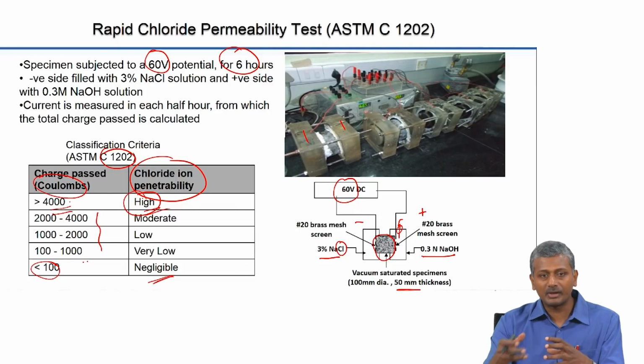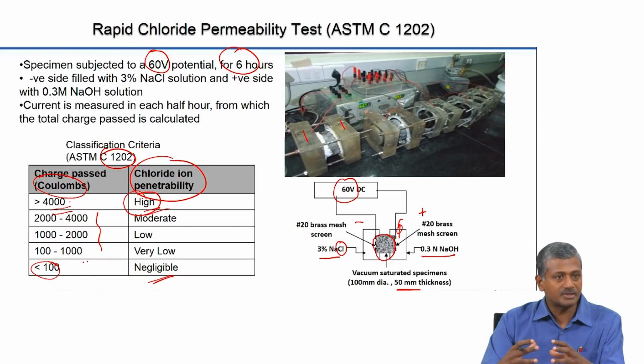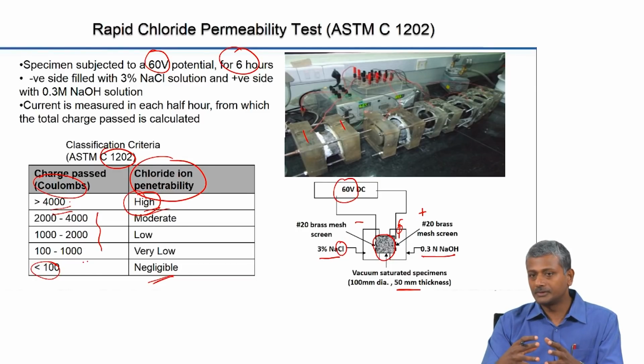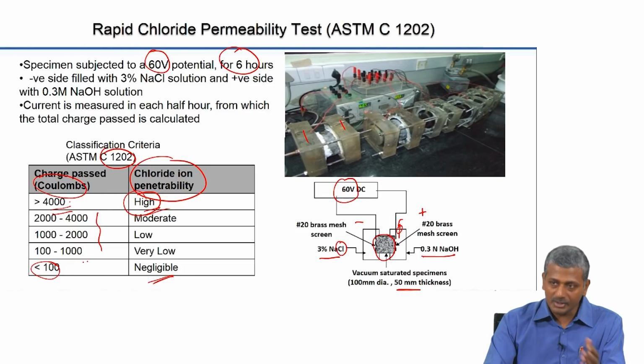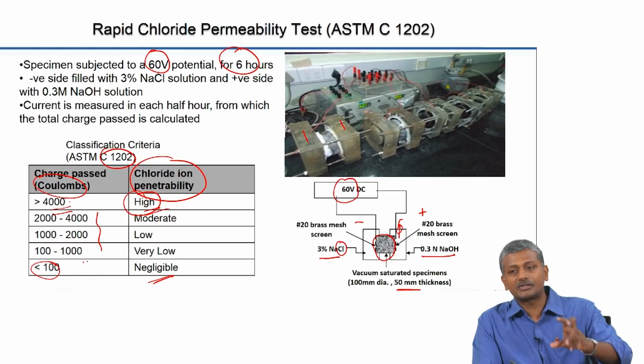The other aspect is you need to saturate the specimen before it's used in this test, so that you don't have other mechanisms also. Already it's a complicated process. There's migration, there's diffusion, all kinds of things are happening. If you have a dry specimen, there'll be absorption also. So you need to ensure that the specimen is saturated. Okay, and so the procedure with which this test is used also incorporates saturation of the specimen before the test is actually conducted. Okay.